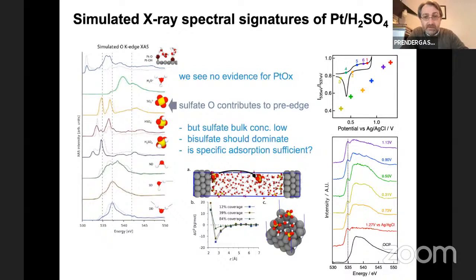We were mainly focused on this oxidative region where we're at positive biases. So we imagine we're drawing anions to the interface, and then we're interested to see what would be the particular species that might contribute to this peak, what do they look like, and so on. So we tried to simulate as much complexity as we think should be present in the system. So the water, obviously, which is, at the oxygen K edge, most of the signal should come from the water. And then the various products of the deprotonation of the acid. So the original acid, which very rarely exists, bisulfate, which has one proton still attached, and then sulfate.